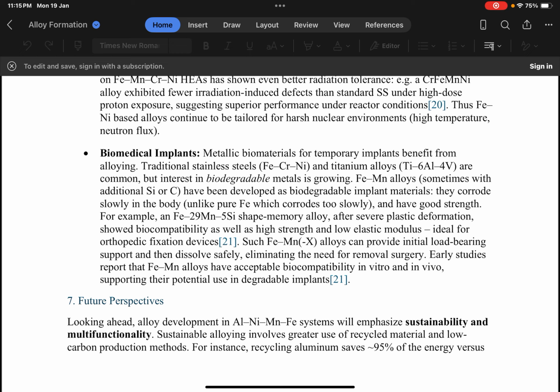For example, an iron-29 manganese-5 silicon shape memory alloy after severe plastic deformation showed biocompatibility as well as high strength and low elastic modulus, ideal for orthopedic fixation devices. Such iron-manganese-X alloys can provide initial load bearing support and then dissolve safely, eliminating the need for removal surgery. Early studies report that iron-manganese alloys have acceptable biocompatibility in vitro and in vivo, supporting their potential use in degradable implants.